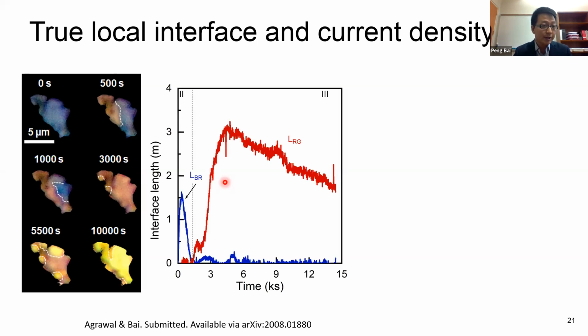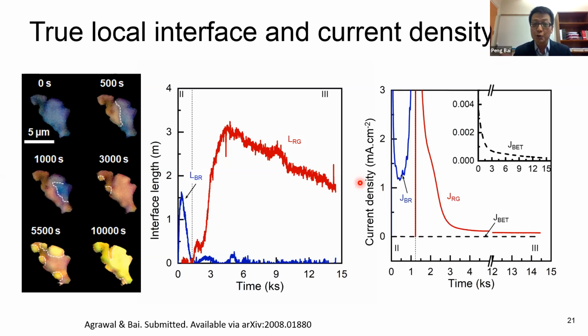So if you do this carefully enough and adopt some Boolean operation, you can see that we can actually characterize the evolution of the interface length. For the interface between the blue and the red, it looks like this, non-monotonic behavior. For the red to gold transition, again, non-monotonic behavior. When you know the interface length and the thickness of the particle, you can calculate the actual interfacial area responsible for this kind of reaction, right? So that you can calculate the true local and working current density.